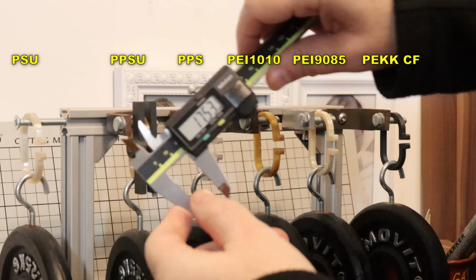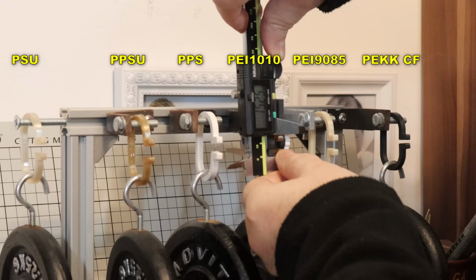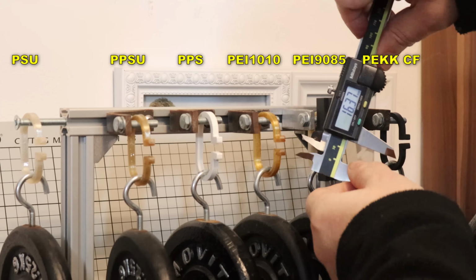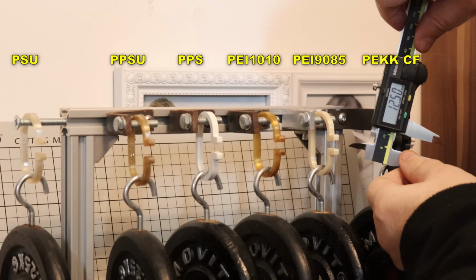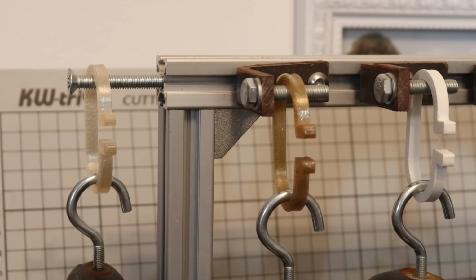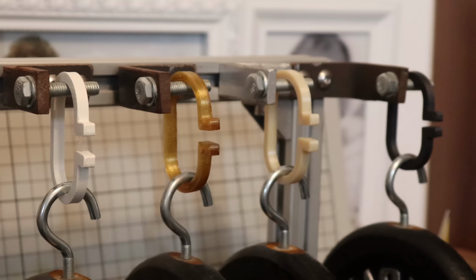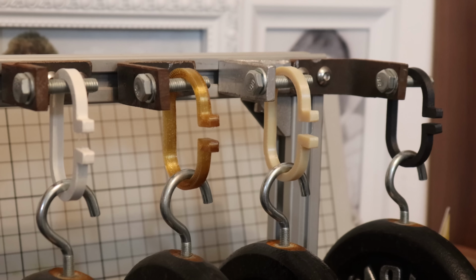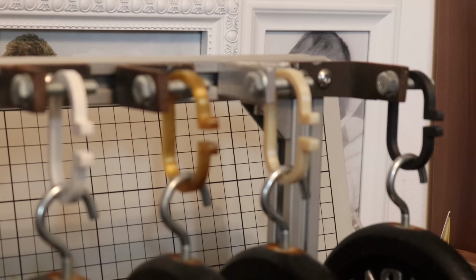16.17, 17.53, 16.94, 15.25, 16.37, 12.50. Quite big start deformation on all 6 test objects, but this is the creep test where the additional deformation in next 5 days is important.